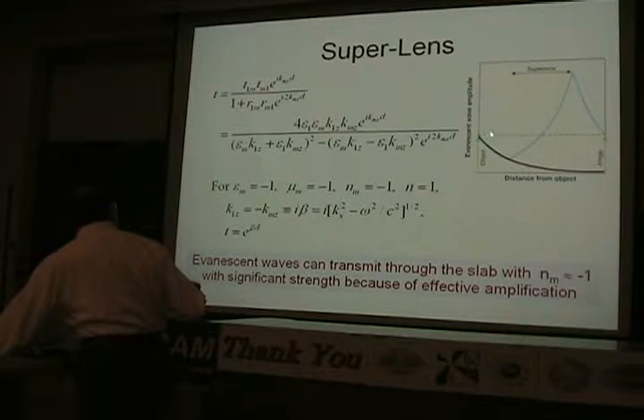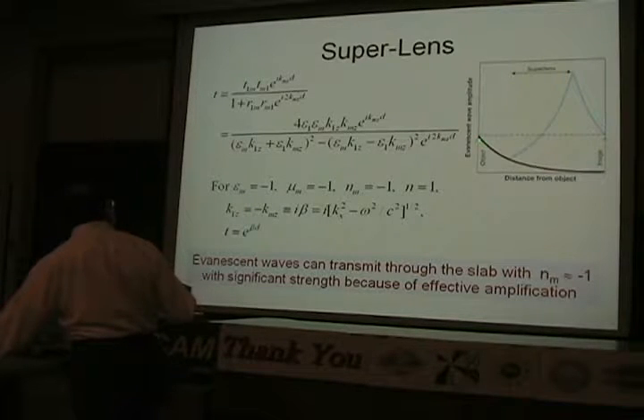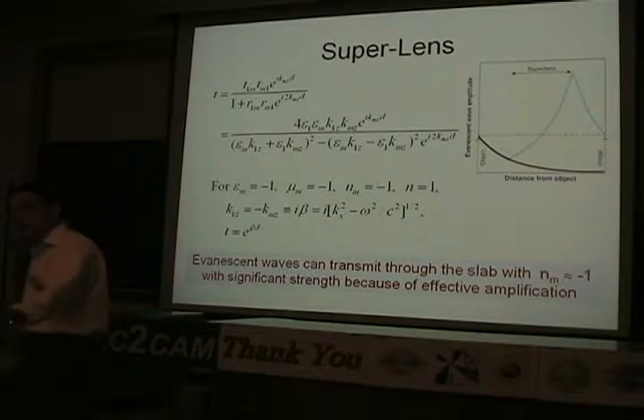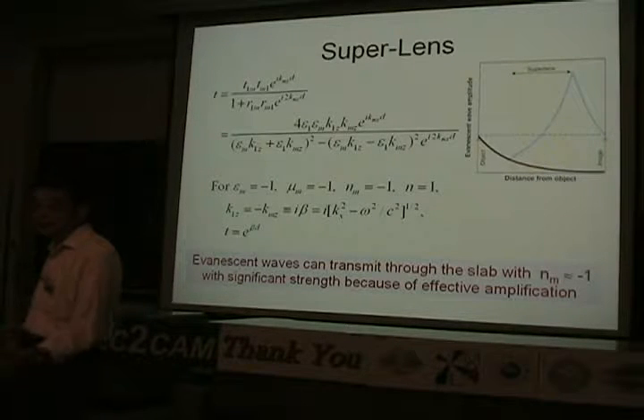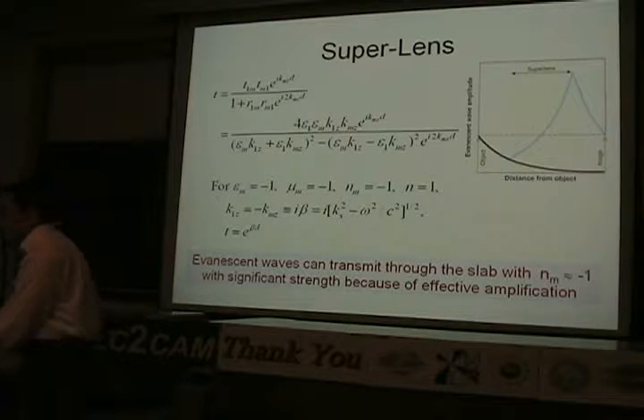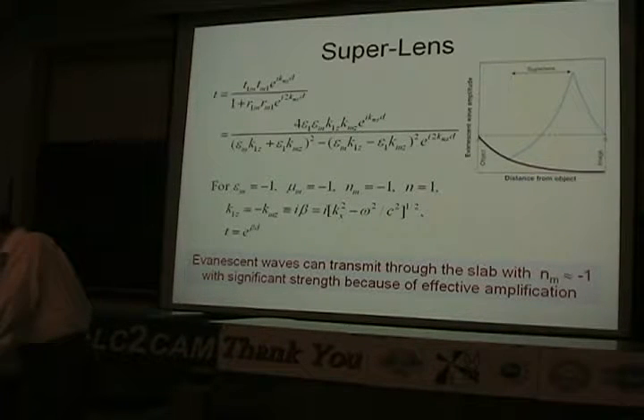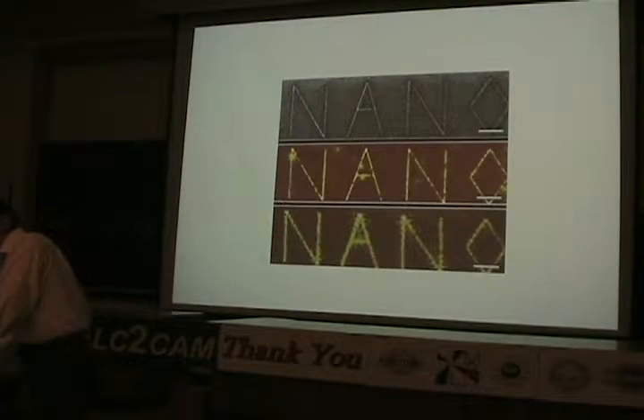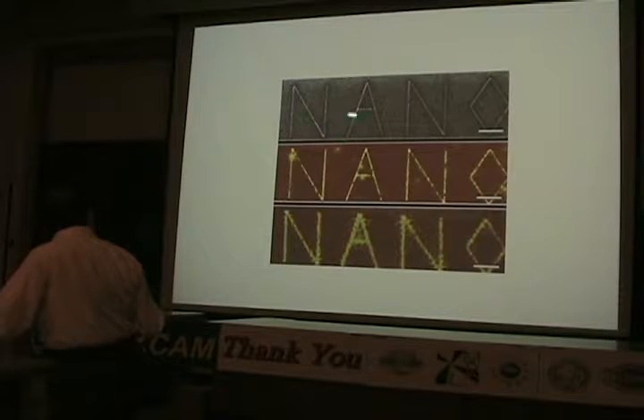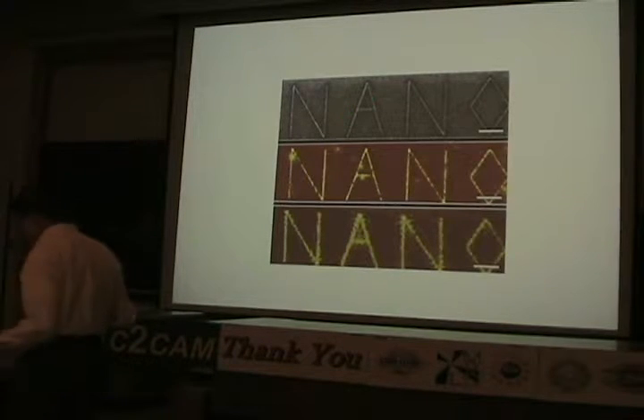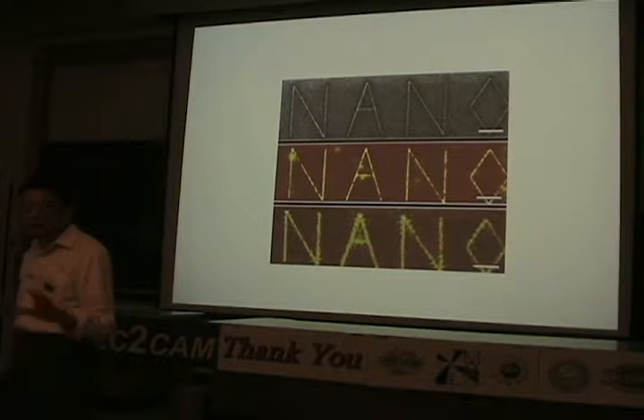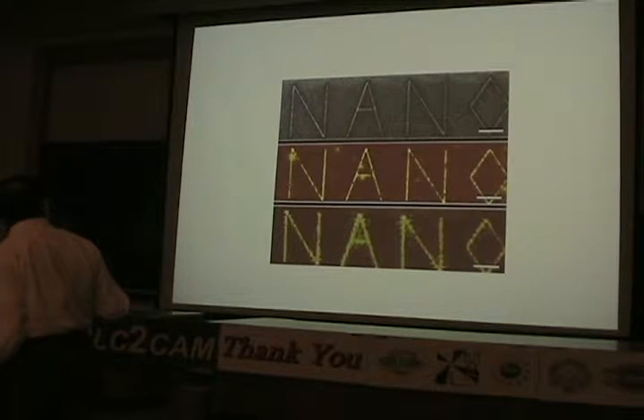And that then allows those waves that cannot propagate from the object to the image start to appear at the image point. And therefore, the resolution can become much better. So this, in a way, has been demonstrated. And as you can see, it's a nanometer structure of the order of 100 nanometer resolution, and this is the STM picture, and this is the AFM picture, and this is the superlens image.